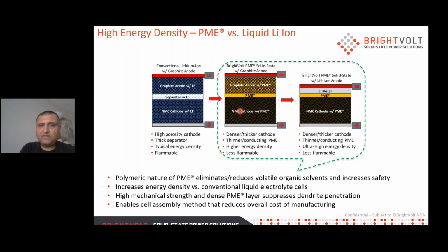One of the most obvious ones is that, as we all know, the electrodes in a battery carry a certain level of porosity. And the idea with conventional lithium-ion batteries is that the liquid electrolyte goes in and fills up those cavities or empty pores in the electrode structure, and that's where you form your ion conducting paths. Now, the benefit of putting an overcoat of the PME on top is, as part of the drying or solidifying process, some of that PME layer that sits on top of the electrode actually interpenetrates into the open pores or the open cavities of that electrode itself, thereby creating multiple conducting paths, as a result of which we get really low interface resistances.